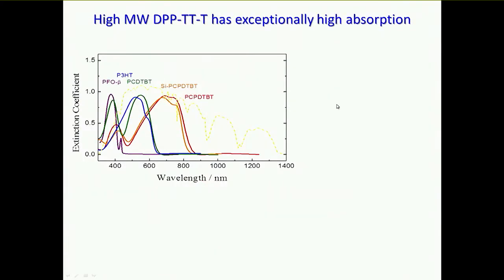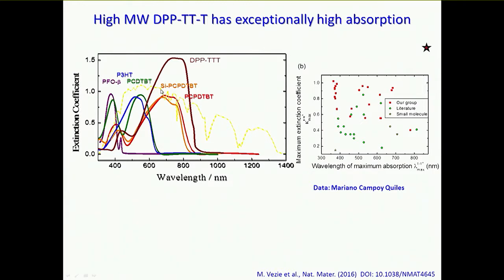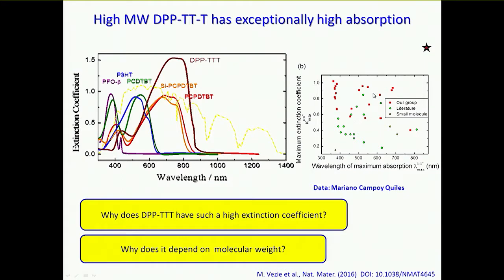The thing that also made it quite interesting was that when we take the best of these conjugated polymers, if we take the imaginary part of the refractive index and plot it, it was showing an extinction coefficient that was almost 40% higher than any other conjugated polymer that we had looked at with spectroscopic ellipsometry before, really giving us something which was almost off the scale of the family of materials we had studied before then. And so we then wanted to ask two questions actually. First of all, why that polymer had such a high extinction coefficient, and secondly, why it depends on molecular weight. But for the moment, I'm just going to focus on the first question, because that by itself is interesting.